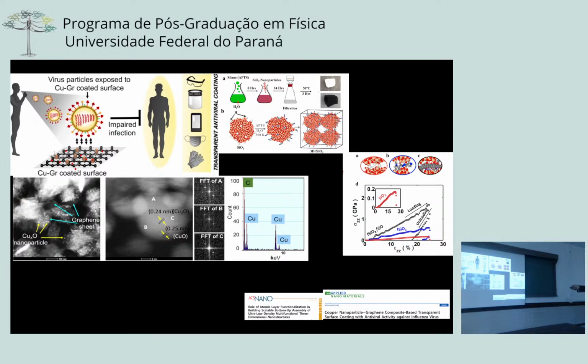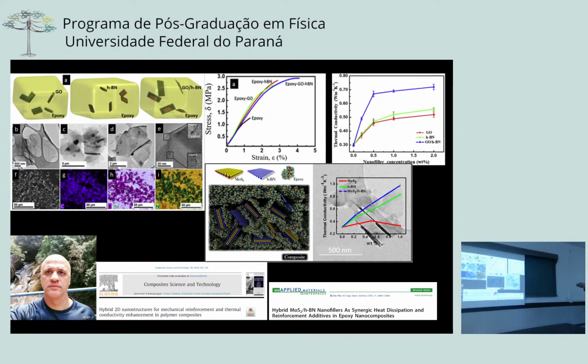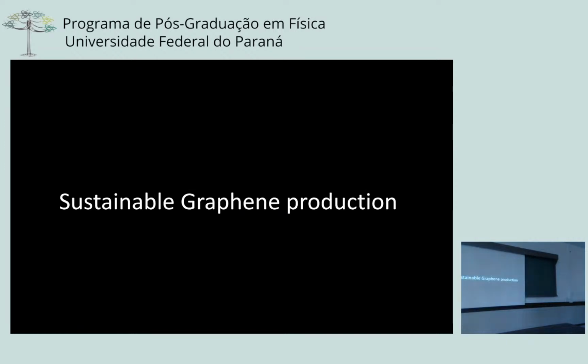Now we utilize that graphene and decorate it, and what you see here is the graphene sheet and you see the small copper oxide particles, which are antiviral, good for killing virus if they come and stick to it. So we started decorating it and coating on top of it, and it can be easily scaled up. You can coat on any object and get this functionality. So as a whole, we can utilize graphene as a template to decorate other material as well. We also use composite, try to reinforce them with different composite.